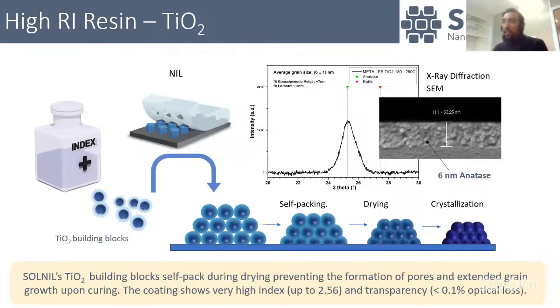So now, how did we achieve such high and low refractive index? The high refractive index, we obtain it using a specific TiO2 formulation. We start not with nanoparticles, it's something smaller. We start with molecular precursors, and we have building blocks which are quite specific. They have a kind of hard core and a soft shell. When you deposit this material by spin coating on a layer, and when you have this drying, the soft shells tend to merge, and basically you end up with a very compact and dense layer, which allows us to get this very high refractive index.